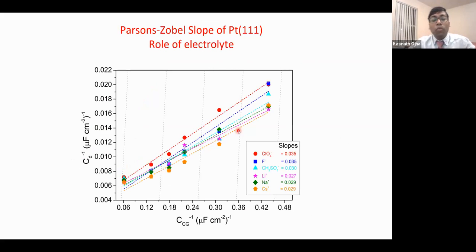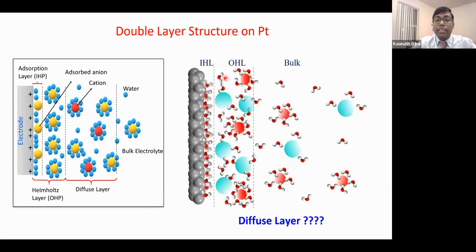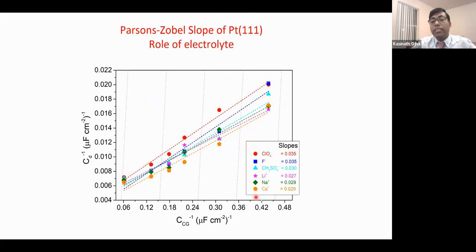So I did even more measurements on that. What I did is, let's say these depend on the ions. The ions are accumulating. So if you change the ions, what happens there? We did change a lot of the ions, but the slope doesn't change much. It's almost the same, within the error range. So the slope doesn't change.